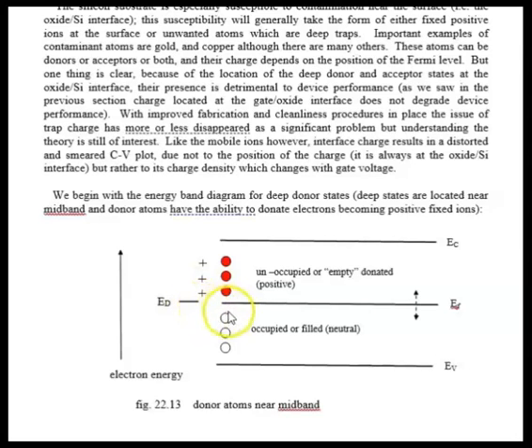And what we're going to say is, and we're going to show this in a little bit more detail later on, that for those states above the Fermi level, these states would be unoccupied. And when I say unoccupied, they're unoccupied by an electron. The donor has an electron to donate, and when the donor atom donates the electron, it becomes unoccupied by the electron. It becomes empty again of the electron because the electron has been donated to the conduction band. Well, it was neutral. If it donates an electron, it becomes positive, and that's shown by these red-filled circles. If the state is below the Fermi level, the state is occupied by an electron. It is neutral and is filled, again, filled by an electron. So this represents donor atoms which have a donor state which is at or close to midband.